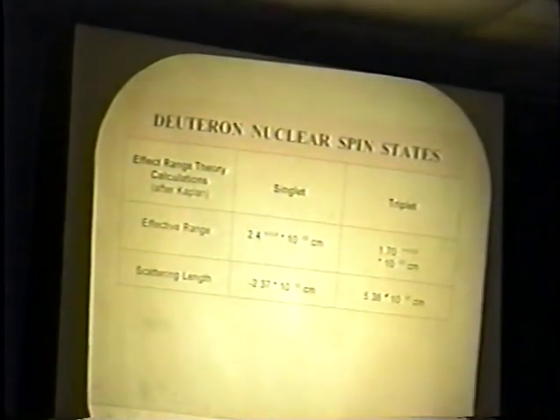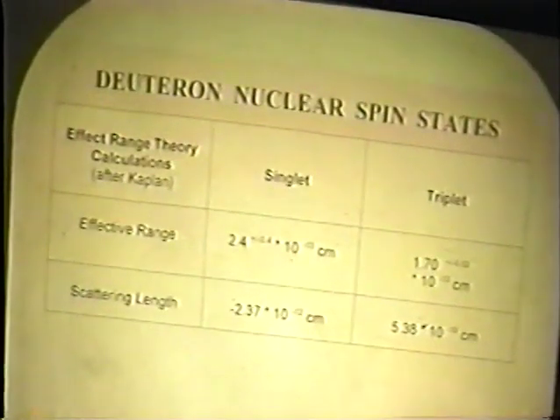On the other hand, there are some reasons why we may be producing them, and it has to do with the spin states. It is well known that the deuteron in the ground state is a mixture of the 3S1 and the 3D1 states. It turns out that in a potential well of about 20 MeV, the first deuteron state is only 2 MeV down. And therefore, we never think of any other states, but there's one more. There's one located at plus 60 keV above the 0 line.